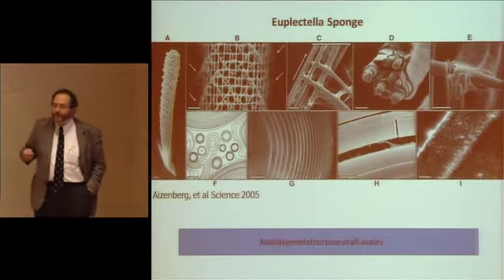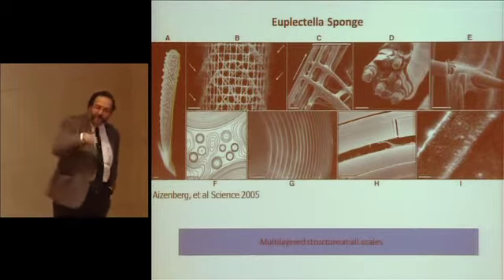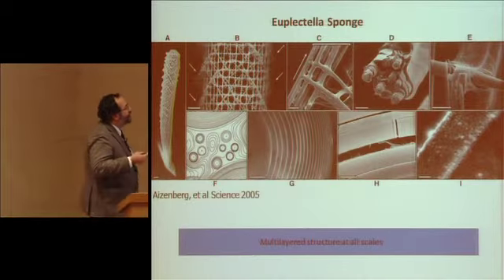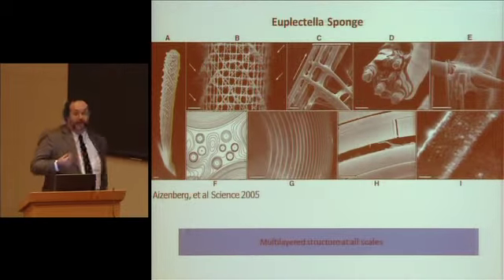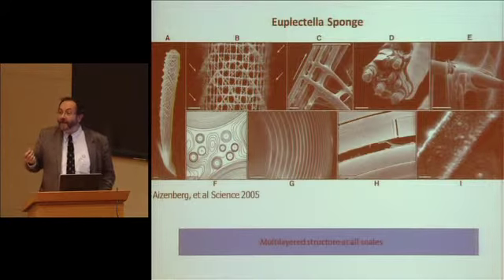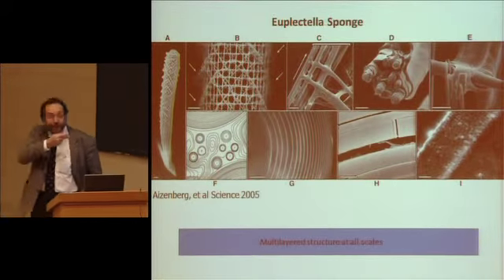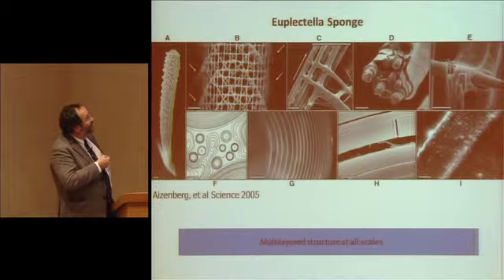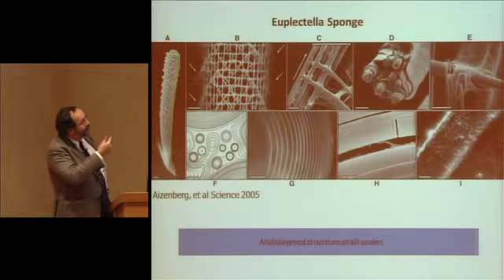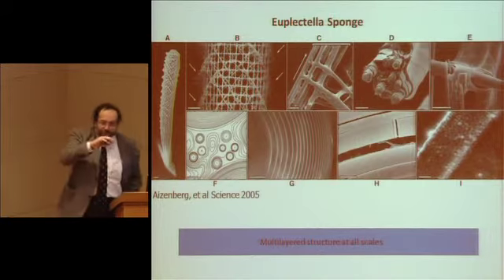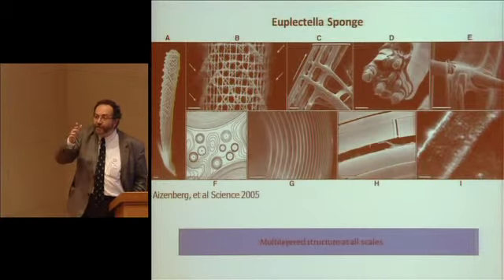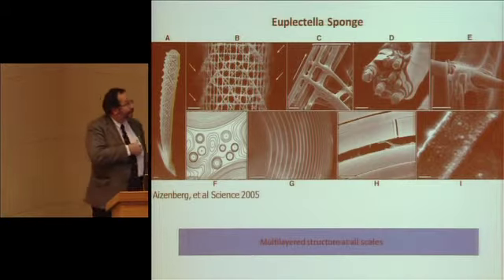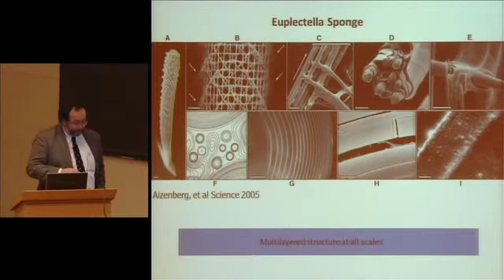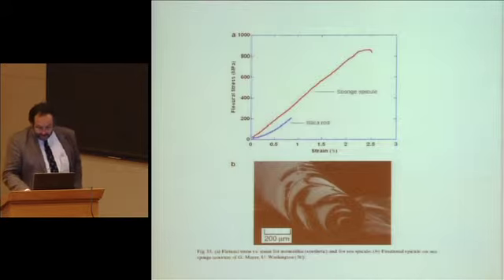The optical quality of the glass is amazing. It may have an influence on the reproductive mechanisms of the shrimp. It's very good optically, but then of course glass is not very damage tolerant. And in fact this cage structure is cabled. It has beams and cables, and each of the beams is an onion peel structure. There are a great number of successive layers of glass layered with organic material, meaning that this material is particularly tenacious.